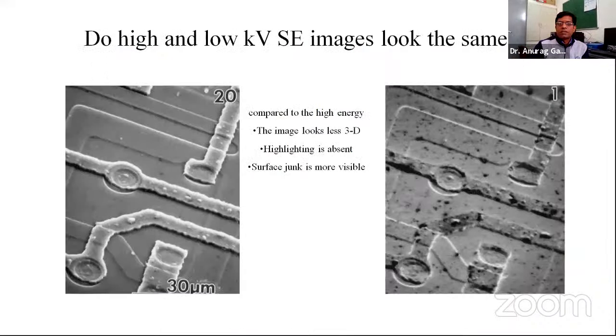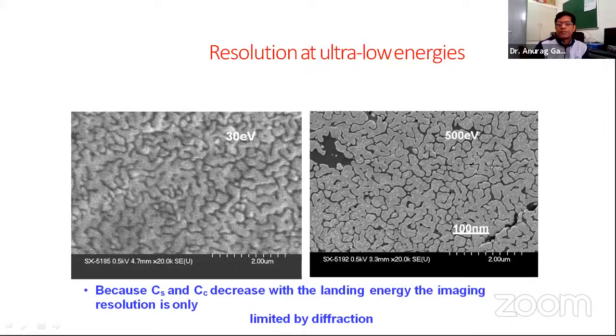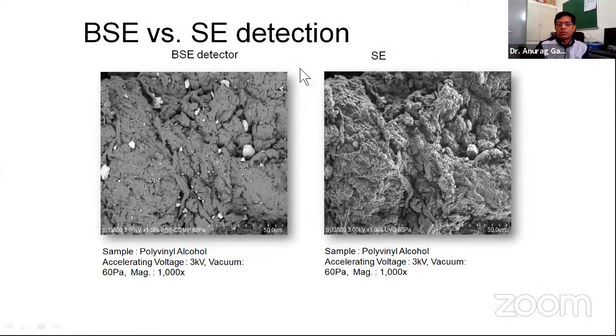These are some images at high and low kV. Naturally the kV here is high, and here it is low. When kV is high, the resolution is better and feature size is clearly seen. So we can see this image has more clarity compared to this one. Similarly, these are 30 eV and 500 eV, which have better resolution. And backscattered versus secondary electron detector: the secondary electron detector images are clearer than the backscattered because they are coming from the depth. So this is the image.